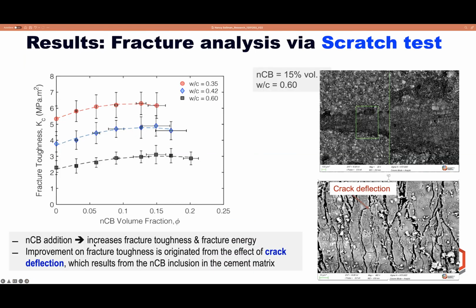So moving now to the effect of nanocarbon black on the fracture properties. The fracture property is the material property that describes the ability of the material to withstand the presence of a crack, and it is a very important parameter as it represents the quality of the binder. By using the linear elastic fracture mechanics method developed by Ulm and coworkers, we evaluate the energy release of the system, which represents the fracture toughness and the fracture energy.